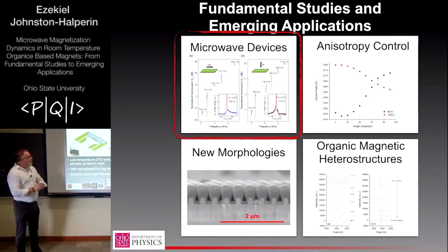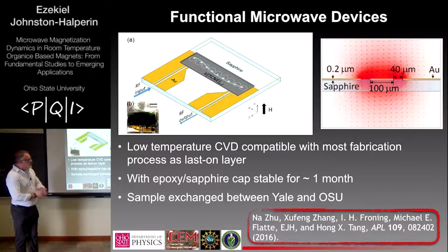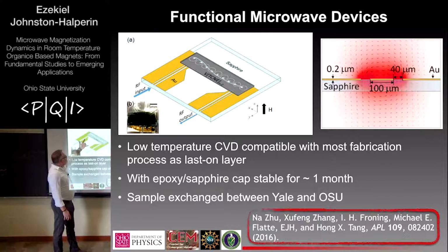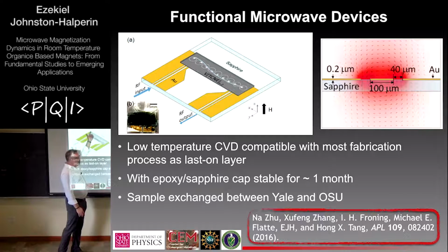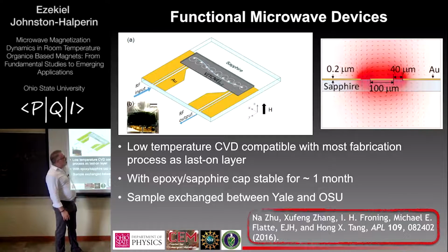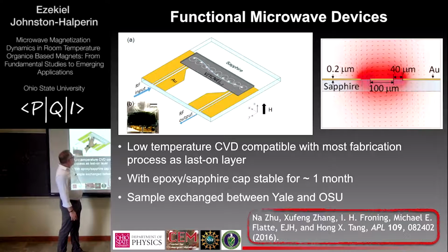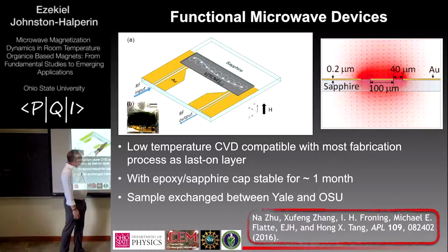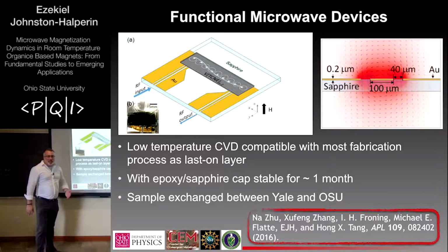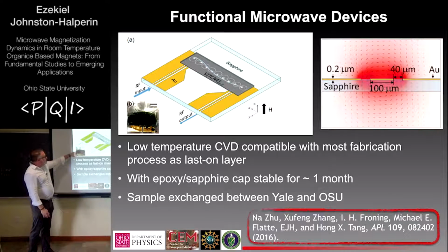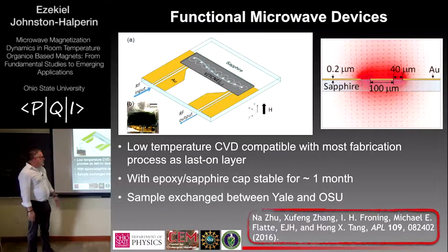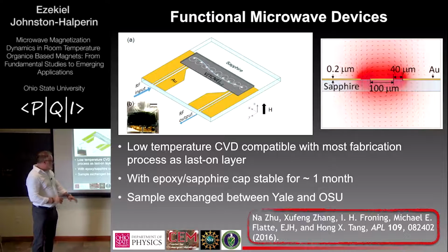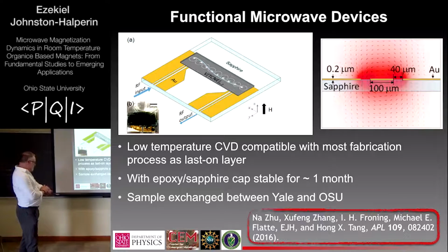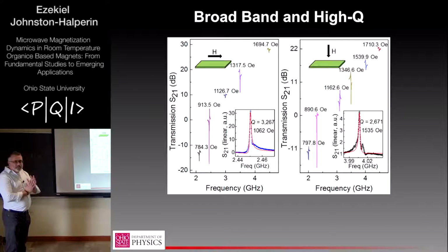The experiment here is basically just taking two microwave antennas and bridging them with a bar of V[TCNE]x. The microwave field from this antenna will excite a spin wave in one end of this bar that then propagates to the other antenna and shows up as microwave transmission. You can see here the real space image of what this looks like. This is a collaboration with Hong Tang's group at Yale and Michael Flatte's group at University of Iowa.